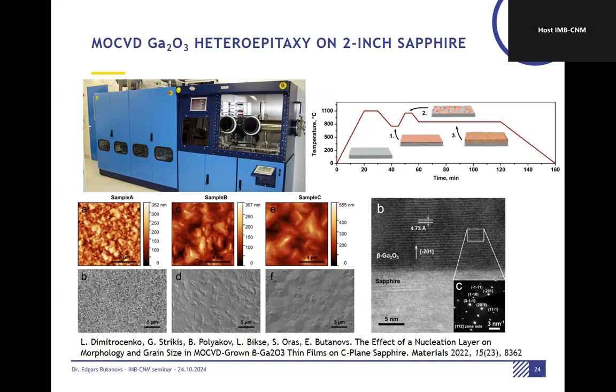And this is the MOCVD tool, as already mentioned, and we are reconstructing the reactor to match oxide processes, because it was designed to have a nitride process, gallium nitride. What is bad with oxide processes in MOCVD is that there are a lot of parasitic reactions, so chemical reactions that happen not on the substrate surface, but just above the surface. That typically leads to lower crystalline quality of the film. So we're implementing some novel solutions to mitigate these parasitic reactions.